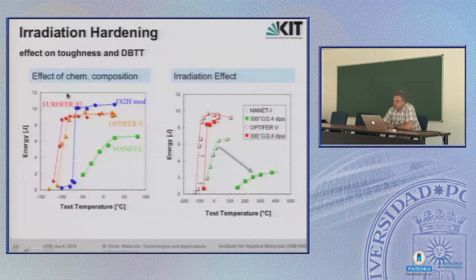On the left-hand side, these are a variety of chromium steels, and you see the difference of their DBTT and Charpy characteristics. That's just due to the alloying, due to the composition. All these materials have been irradiated, and we focus only on two different types of steels, unirradiated here, and after irradiation, a rather big shift of the ductile to brittle transition temperature. This means this steel is not a very good material for structural applications under neutron irradiation. Compared to this steel, the same irradiation campaign, the same irradiation parameters, and the shift is comparably tiny. So alloying certainly has an effect on all of this.